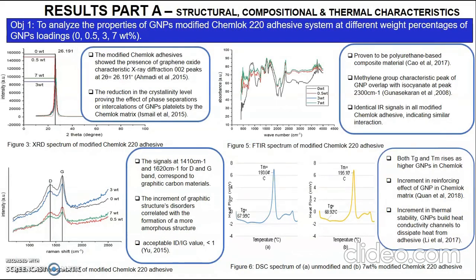Apart from gel time, analysis is also important to achieve objective 1. From structural analysis, the XRD 002 peak at 2 theta equal to 26.191 degree shows the presence of GNP. And from the Raman, the D and G peaks show they correspond to graphitic carbon materials. Even though the ID over IG ratio is quite high, it is still acceptable as it is lower than 1.